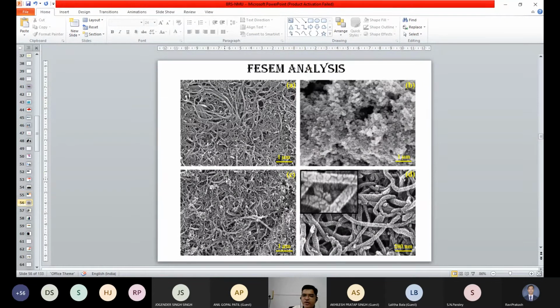Then here you can see the surface morphology through SEM analysis. This is the carbon nanotube. Image B is vanadium sulfide coated on the stainless steel without carbon nanotube, and you can see smaller particles coated on the stainless steel. But whenever we coat this vanadium sulfide on the carbon nanotube, as you can see in the last image, it is very uniformly coated on the carbon nanotube, so that this high surface area can be utilized for the supercapacitor application.